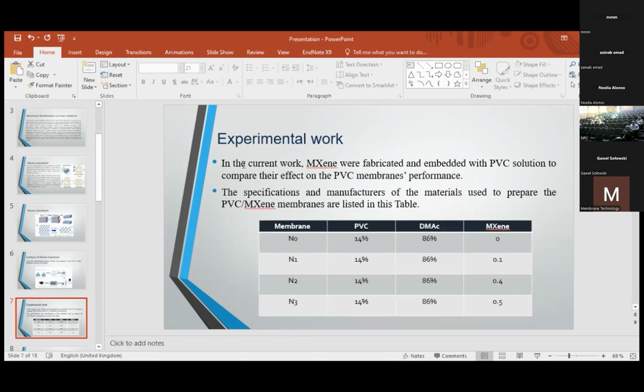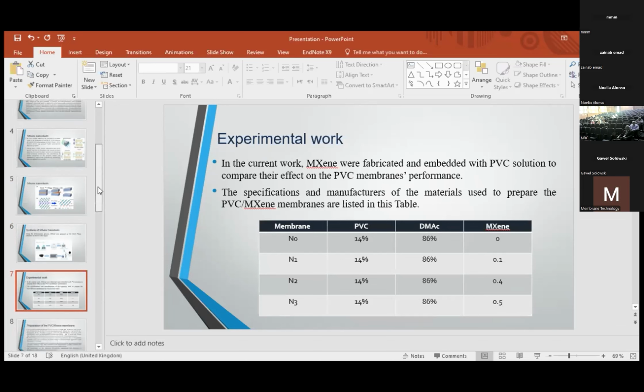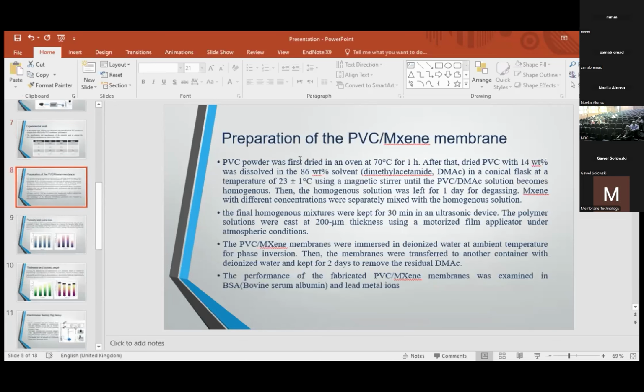In the experimental work, MXene was fabricated and embedded with PVC solution to compare their effect on the PVC/MXene membrane's performance. The specifications and manufacturers of the materials used to prepare the PVC membrane are listed in this table, which is 14 weight percent PVC and 86 weight percent DMAC with the different concentration of MXene nanosheets. For the preparation of the PVC MXene membrane, the polymer solution was cast at 200 micrometer thickness using a motorized film applicator under atmospheric conditions.